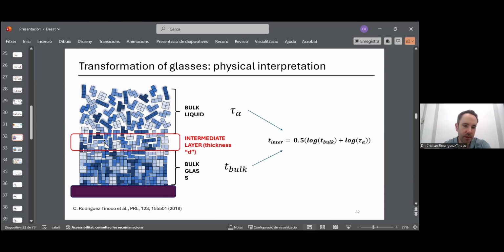Okay, and if we do this, we have seen that it can be used to obtain this growth front velocity. So summarizing, the growth front velocity comes from the fact that this intermediate region, this interface between liquid and glass, is governed by a time scale from the glass and a time scale from the liquid.